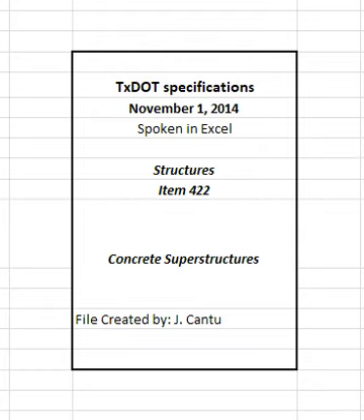Use one of the following water curing methods for final curing. Keep all exposed surfaces of the concrete wet continuously for the required curing time. Use water for curing that meets the requirements for concrete mixing water in section 421.2.5, Water. Do not use seawater or water that stains or leaves an unsightly residue.